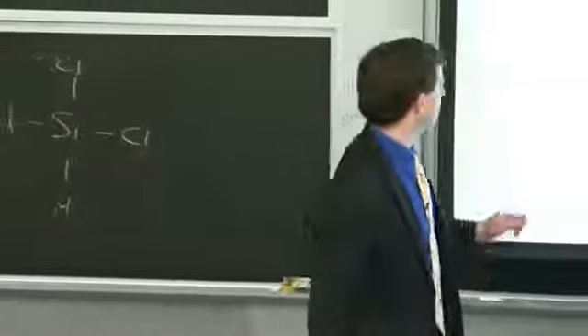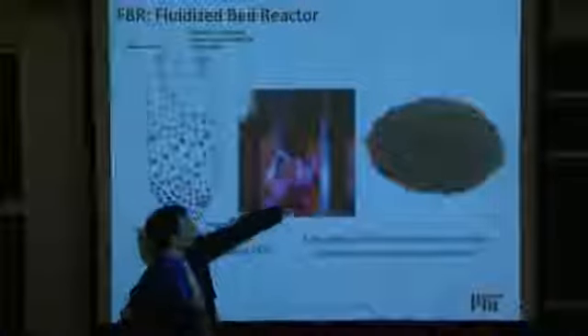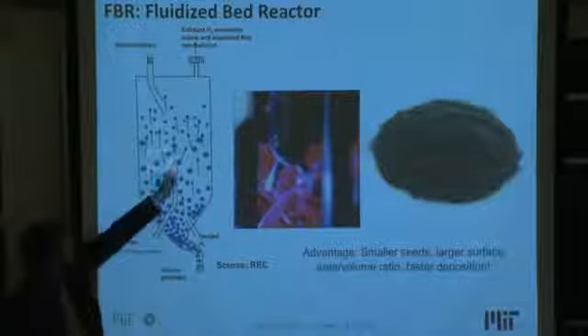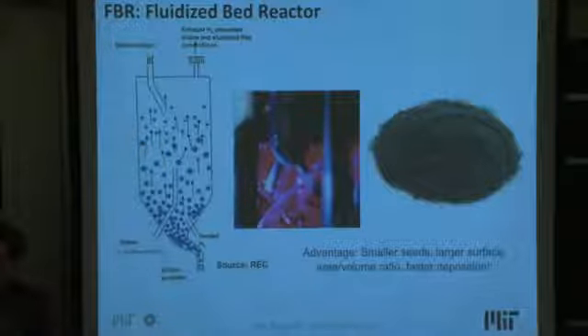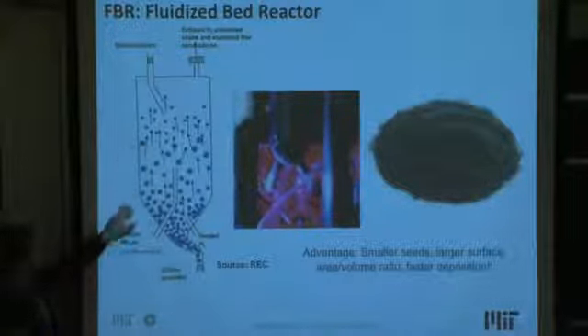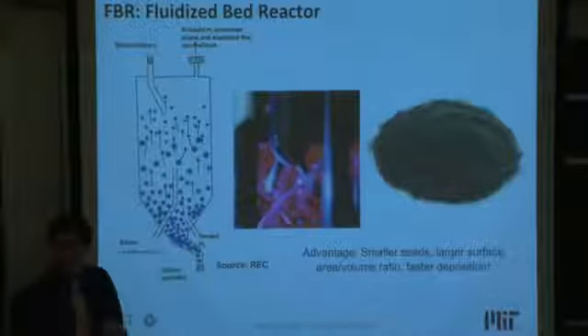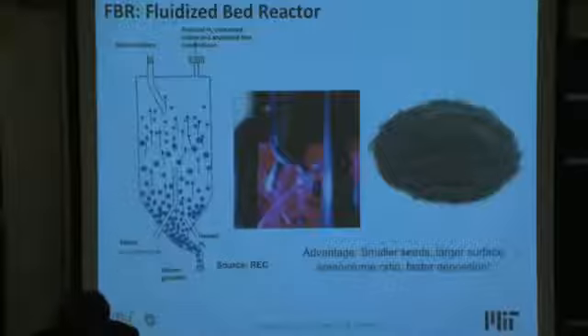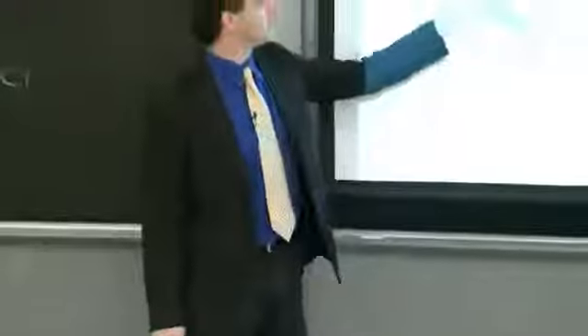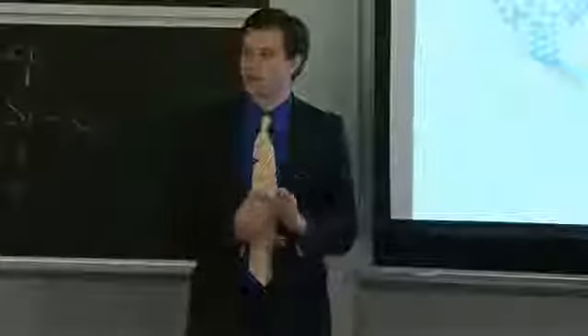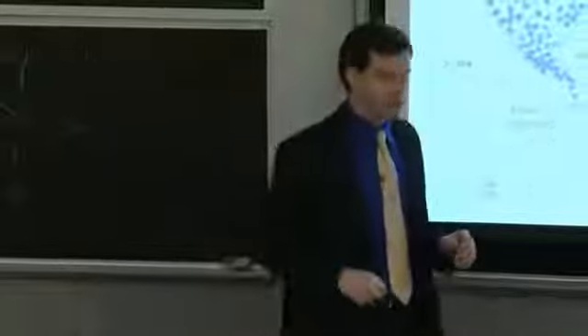And so what these folks decided was, we're going to introduce small silicon granules into this vessel, into this evacuated chamber. And here's the evacuated chamber right here. And we're going to flow silane gas into the system right here. The smaller particles are going to go higher up because of this flow of gas coming from the bottom. And those will grow and eventually settle down here where we can extract them from the bottom. And so we'll wind up with these beautiful little silicon granules, these ones shown right here, which I'll pass around as well. Those are coming from a fluidized bed reactor. They're nice, beautiful, spherical granules that are grown a lot faster, a lot more silicon is deposited per unit time than through the Siemens process as shown there in the back.